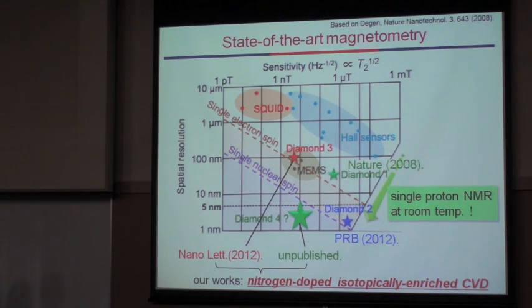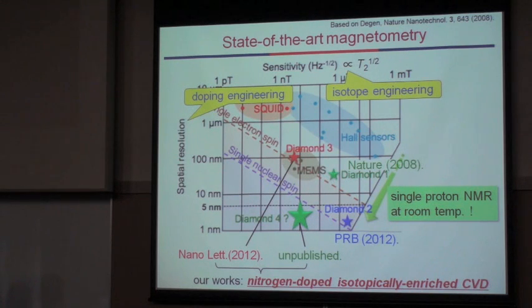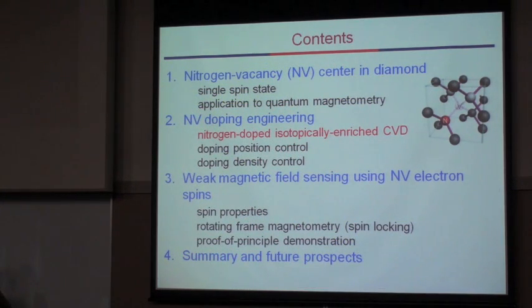Our purpose is to achieve higher performance of diamond sensor to realize single proton spin detection. Our technique to achieve higher performance is nitrogen-doped isotopically enriched CVD. We can achieve higher performance by developing isotope engineering and doping engineering in the nitrogen-doped isotopically enriched CVD method. Today, I'd like to show you the result of our doping control technique using nitrogen-doped isotopically enriched CVD. After that, we show the first demonstration of magnetometry using our NV center sample.